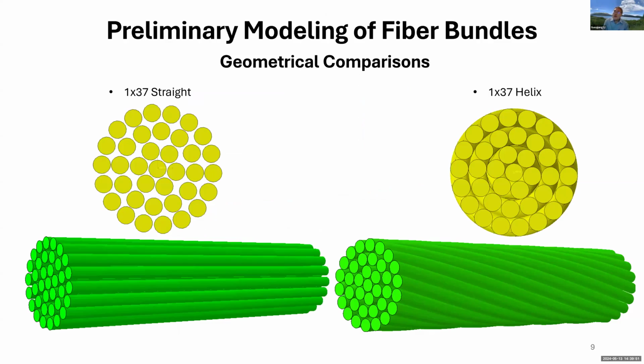Okay, once we know we have a good polymer, the other side is that we try to find a good matchable fiber. As you already know, for lots of synthetic fibers like glass fibers and carbon fibers, their tensile fracture strength is very low. For example, glass fibers usually fracture at about 3 to 5%. In order to input more energy, the fiber cannot fracture during the pre-stressing process. So we're trying to see if we can further increase the fiber bundle fracture strength.